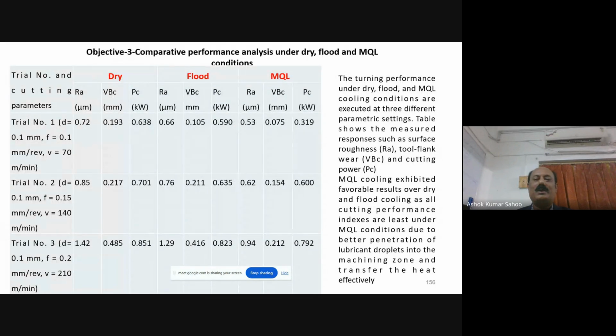A comparative performance study has also been carried out under dry, flood, and MQL environments at a particular machining parameter condition, that is, depth of cut of 0.1 mm, feed of 0.1 mm per revolution, and cutting speed of 70 meters per minute. At 70 meters per minute cutting speed, we observe less roughness, less flank wear, and less power consumption under MQL environment as compared to dry and flood during machining of titanium alloy.